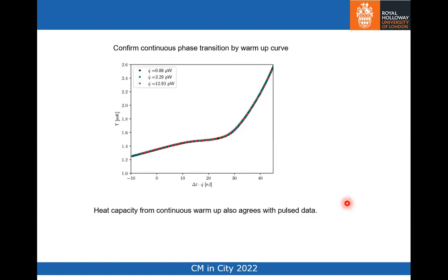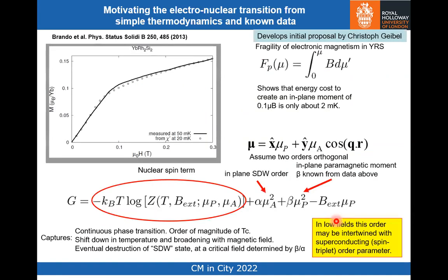So you might ask yourself the question, you're claiming that this is a continuous phase transition. Why isn't it just a first order transition that's broadened in some way? So what we do is we warm through the transition at different rates, and we find that changing that rate by more than an order of magnitude, the data is the same, and the heat capacity derived from this continuous warm up agrees with the pulse data. And so we believe on experimental grounds that it's a continuous phase transition.